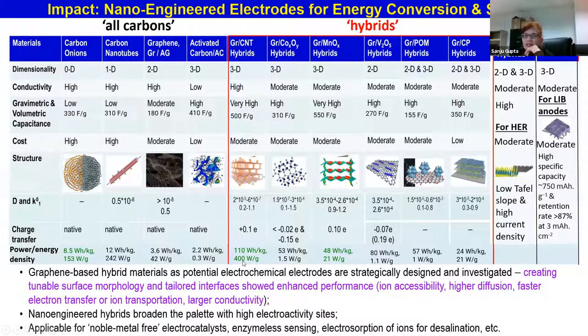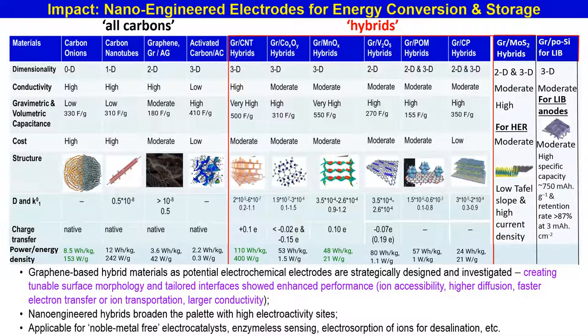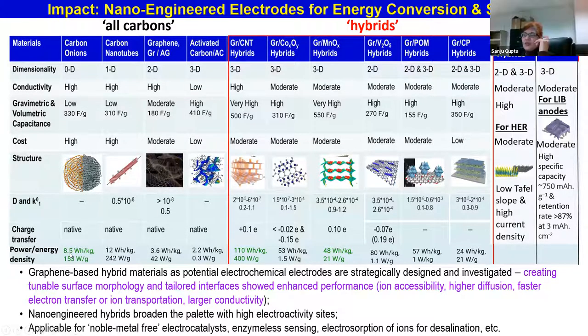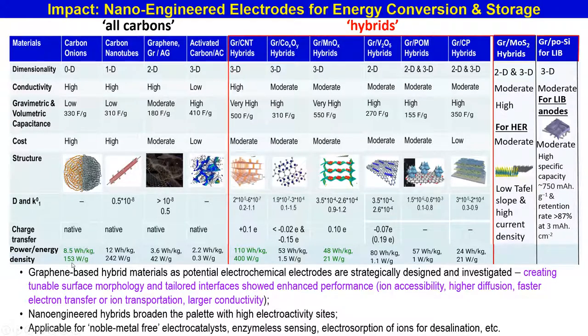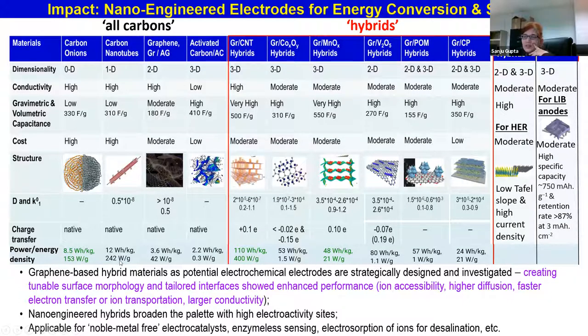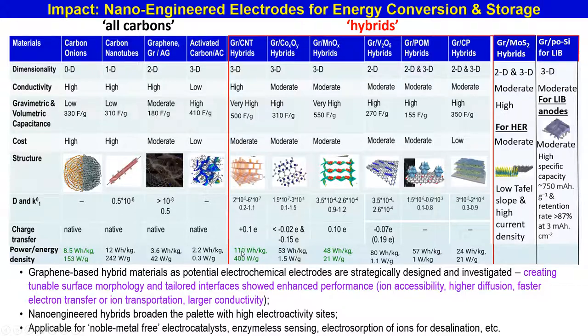Why are they not similar? In the carbon onions case, it's 8.5 watt hour per kilo and 153 watt per gram. In the hybrid, it's 110 watt hour per kilo and 400 watt per gram. Why don't they go hand in hand? You are saying the carbon onions and graphene carbon nanotube hybrids? Yeah. What I'm saying is the watt hour per kilo increased from 8.5 to 110, but the watt per gram changes only from 153 to 400. Why is that ratio not the same?